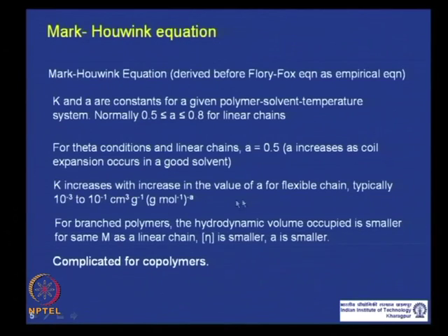A is more informative in polymer characterization, and you will find that A is probably more important than K between these two constants. Now, for branched polymer, even if you consider theta condition, the expansion factor will be lower than 1 if you compare with a linear polymer. So, your A value could be lower than 0.5.